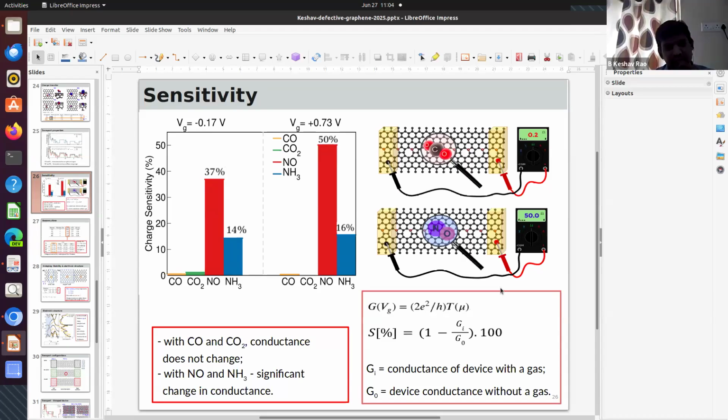Sir, I want to ask about the pseudopotential that you have taken. Is it a GGA pseudopotential, a norm-conserving potential? GGA was taken, and van der Waals is also taken, because gas molecules need to get adsorbed. Without van der Waals, the interaction cannot be considered or may not be the best one. So whenever gas molecules are required to be adsorbed, van der Waals must be taken, and GGA is also considered.